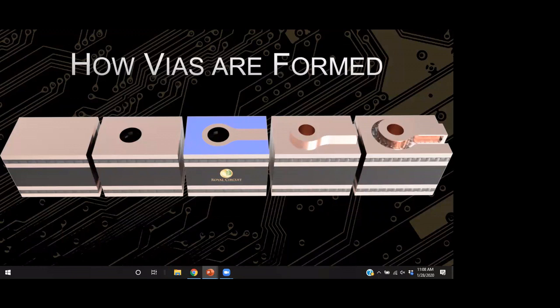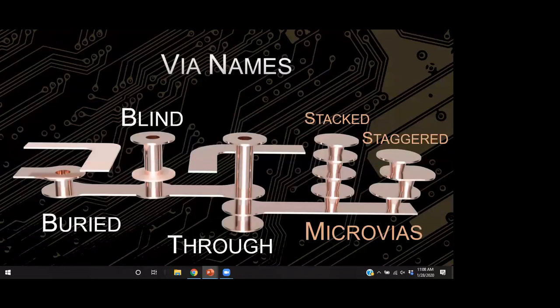Next to that, we're going to cover the rest of the board in a film to protect it. And now we're going to plate additional copper. And this step adds copper to the surface and also forms the barrel walls of that hole. And then the last step, we're going to be etching off the copper to create the via that you designed. And so that's just the basics of what it takes to make one via. And this is just a standard via, but once we start using blind or buried, now we have to start building your board in multiple stages. And here's where we start to increase yield risk, turn time, and cost starts going up.